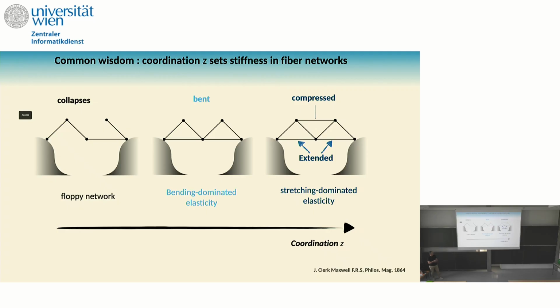And this has been worked out a long time ago, where people have been fascinated about making bridges, right? And the idea is the following: I will add more constraint. If I add more constraint, then I end up with a structure like this one, that is rigid, but it's dominated by the bending. So here, if I apply a deformation to that bridge, the bridge would bend a little bit. I would not stretch the links. I would firstly bend the links. This is a bending dominated elasticity. If I keep increasing the coordination number or adding more bars, then I end up with an over-constrained situation where now if I apply a deformation, I'm not able to first bend the bars, but rather I would stretch the bars between my vertices. And this is a stretching dominated elasticity.